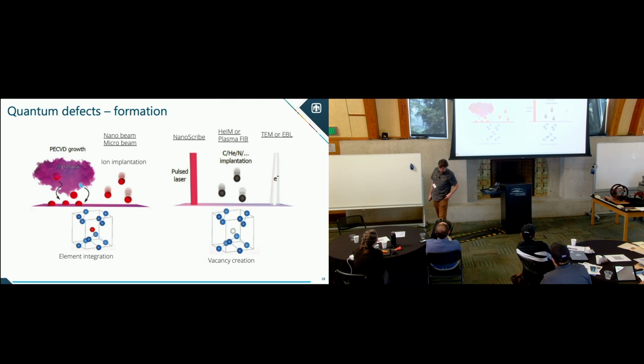Particularly for the nitrogen vacancy, which, as you know, consists of two things: a nitrogen and a vacancy. You have to be able to make both of those in diamond. The way you integrate nitrogen into a diamond is you can either do it during the growth phase, and the ideal way to do that is plasma-enhanced CVD growth. When you're doing that growth, you dope diamond on the order of 1 part per million with nitrogen, and then you'll have nitrogen within the lattice. The other way to do it is with ion implantation, and this is slightly less ideal when doing super sensitive experiments, because that implantation can also cause damage, more damage than you want. You want to be able to controllably damage this. But we do this a lot too.